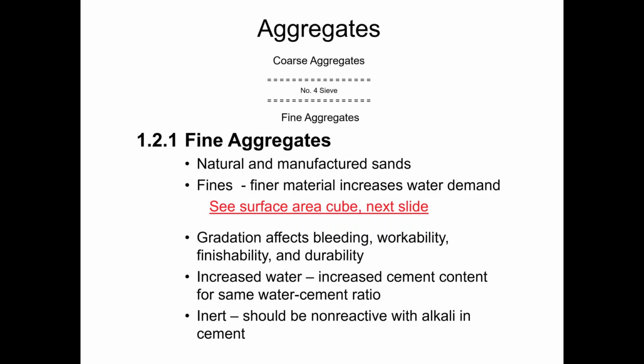Another important material property for fine aggregates is that they should be inert in the sense that they do not react chemically with the oxides that are present in the cement. So generally it is the potassium and the sodium oxides in the cement that tend to react most commonly with our aggregates. And so there are a variety of ASTM tests that can be conducted to determine just how reactive an aggregate source is. Ideally, we want to use aggregates that have been tested and show that they are not reactive with the potassium and the sodium oxides that are present in the cement.